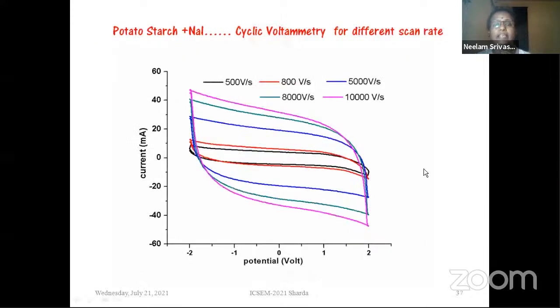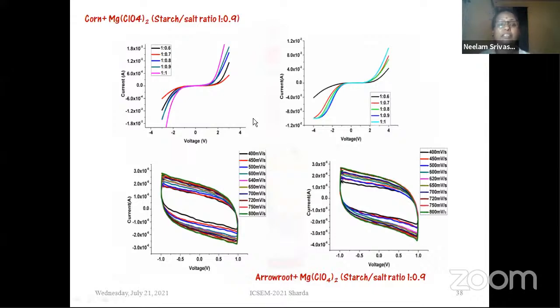Similar kinds of studies have been observed for the other systems: potato, and this is for a different corn starch system. I'm just showing different data. This is for the arrowroot starch system, and for magnesium salt. You can find that everywhere the desired properties are very well maintained. Of course, some difference in the scan rate is observed. That is very obvious, since it will differ depending upon the salt and the salt movement. Of course, it has to be different. So there is a difference, but quite good behavior has been observed for all the systems.